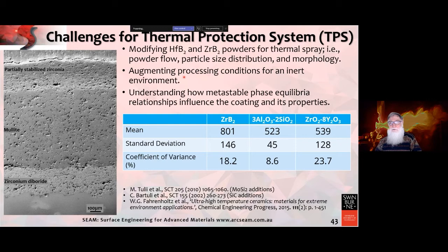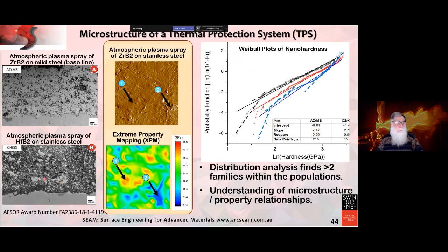Within our lab, we have a very simple cap system, very simple, so that we can produce an inert environment. Because the zirconium diboride is extremely difficult to spray and be retained in its native zirconium diboride. It has a tendency to oxidize severely. So what we've done is a baseline material on mild steel. There's a hafnium diboride on stainless steel. Again, we carry out the microstructural cross sections, the property mapping.